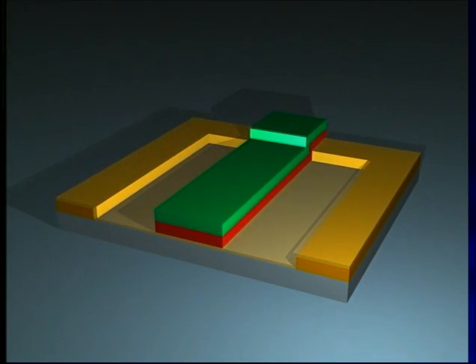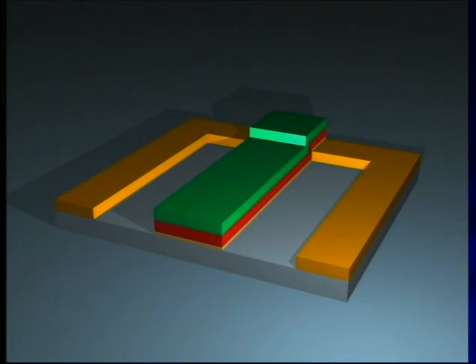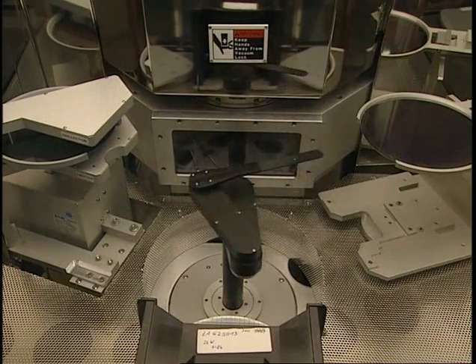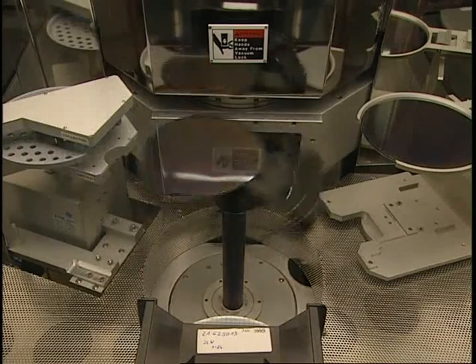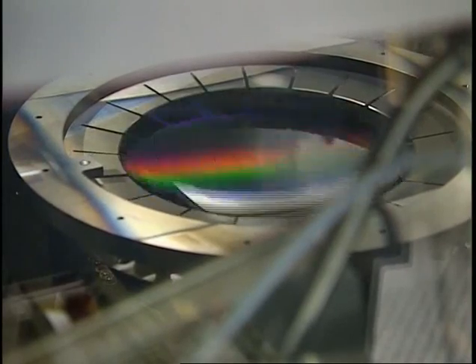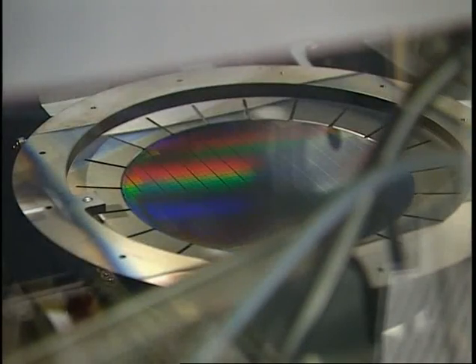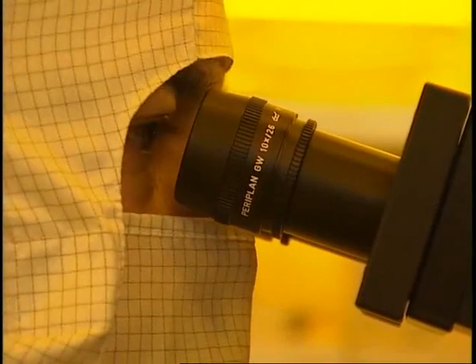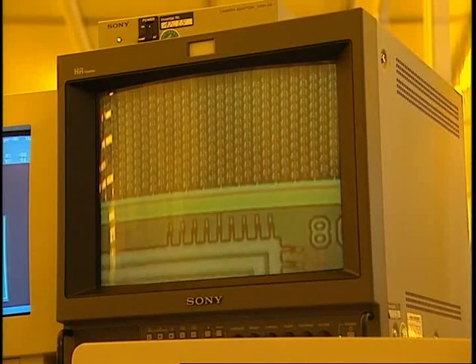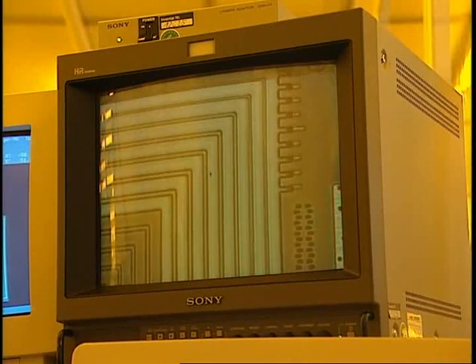Then, the polysilicon and the thin oxide layer are etched off. They both remain intact only in the middle under the resist layer. In the next step, an ion implanter shoots impurity atoms into the silicon. This changes the conductivity of the exposed silicon by fractions of a micrometer. Structure widths, distances, and cover precision are constantly checked.